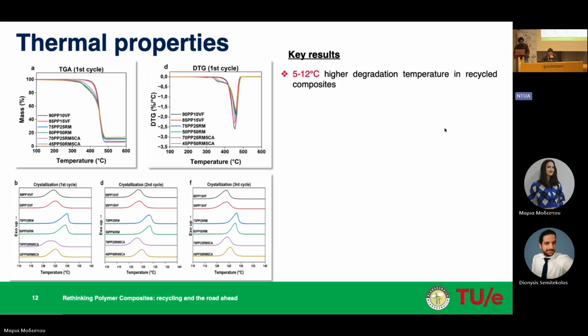And also, due to the addition of these recycled materials from wind turbine blade waste, we can actually see a significant increase in the degradation temperature. The numbers themselves say that the degradation temperature increased by around 5 to 12 degrees Celsius, which is actually a significant number.